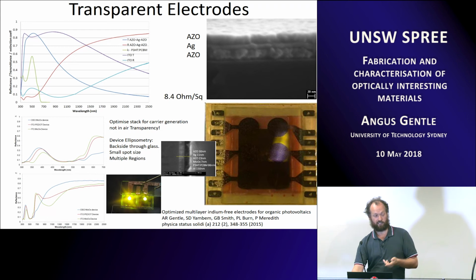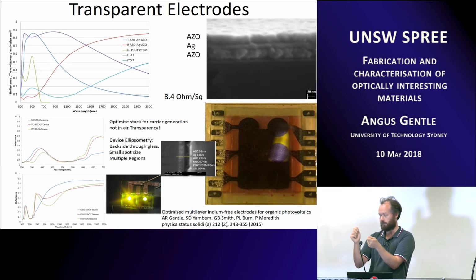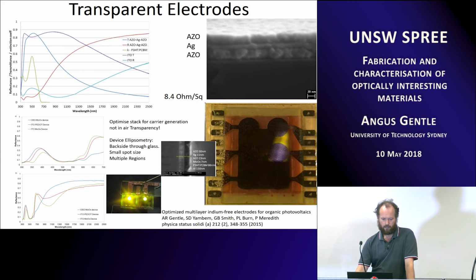So the ITO sheet resistance was 15 ohms per square. Ours was 8.4 ohms per square, so significantly lower. You could bend it, even bending it quite tight, you'd still stay below 10 ohms per square because you've got a very, very thin ductile material between the oxides.